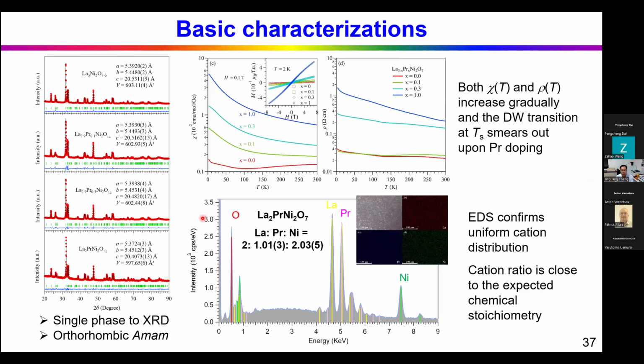After preparing these polycrystal samples, we performed basic characterizations, including XRD. The XRD confirmed it is single phase and has an orthorhombic structure. And this is the magnetic susceptibility and resistivity. Basically, the resistivity increases and the magnetic susceptibility also increases with increasing doping. This is understandable because praseodymium has a magnetic moment, and also the resistivity increases and the density wave transition becomes very weak up to 1/3 doping.